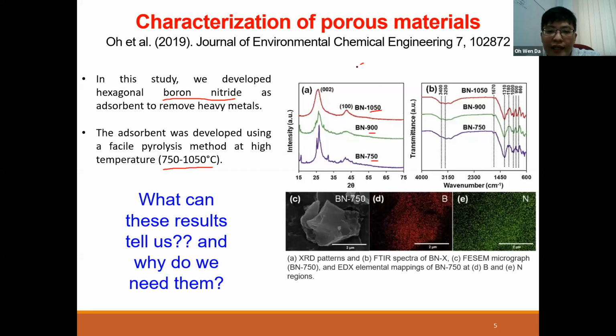to 1050, is to look at the XRD. The reason why we need the XRD is because, as I said, this is an inorganic adsorbent. And for an inorganic adsorbent, XRD is very important because it tells us whether we have successfully developed the adsorbent or not. So if you look at the XRD for 750 to 1050, how can I tell I have successfully prepared this boron nitride? Very simple. I compare it with the library.